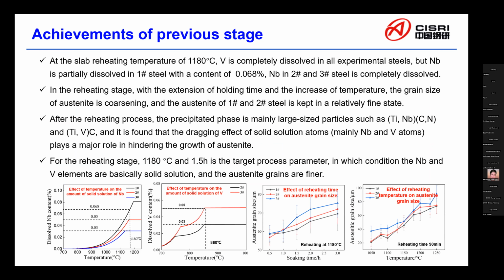And here are also the achievements of previous stages. At the slab reheating temperature of 1180 centigrade, vanadium is completely dissolved in all experimental steels, but niobium is only partially dissolved in number 1 steel with a content of 0.068%. Niobium in number 2 and number 3 steel is completely dissolved.